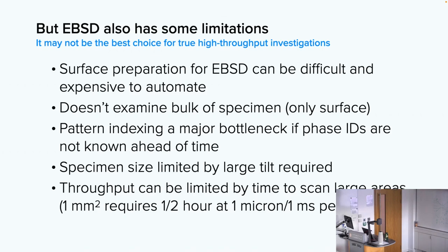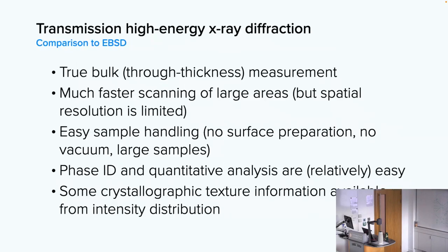Another limitation of EBSD is that it doesn't examine the bulk microstructure, right? It only examines the surface. But if you're doing mechanical properties on samples which are a few hundred microns thick, gradients in that microstructure through the sample might be really important. And EBSD is not going to be able to tell you about those if you're only looking at it in plan view. Another problem was pattern indexing. So if you have unknown crystalline phases, EBSD pattern indexing is pretty straightforward if you know what phases are present. But if you don't know, and particularly if you have unknown phases, then that's a major, major challenge and is a research project in its own right.